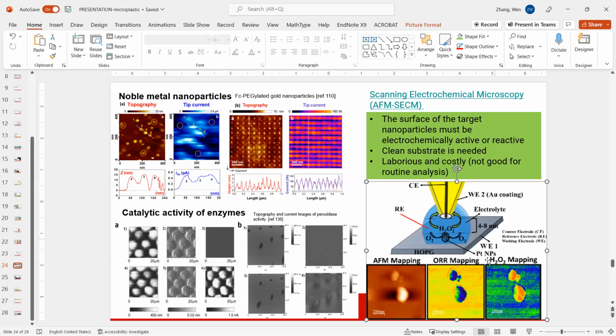For example, the image on the bottom right shows a very good example where you have a catalyst right here, platinum nanoparticles or another kind of particle. In the matrix, you have electrolytes that would react. If you apply a voltage onto the sample, it would react with oxygen and produce hydrogen peroxide. That hydrogen peroxide will migrate to the tip, react with the tip, and generate tip currents, right? This is the idea. This is one of the designs that you can use. Based on this design, we can generate so-called oxygen reduction reaction mapping, depending on where you measure the currents.